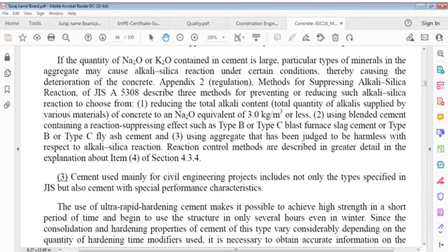If quantity of Na2O or K2O contained in cement is large, particular types of minerals in aggregate may cause alkali silica reaction under certain conditions, thereby causing deterioration of concrete. Appendix 2 describes methods for suppressing alkali silica reaction, with three methods to choose from. Number one, reducing total alkali content, that is, total quantity of alkali supplied by various materials of concrete, to 3 kg per cubic meter or less in Na2O equivalent.